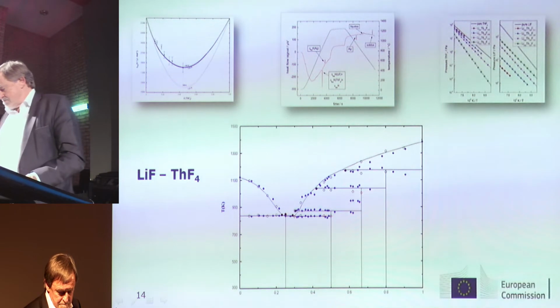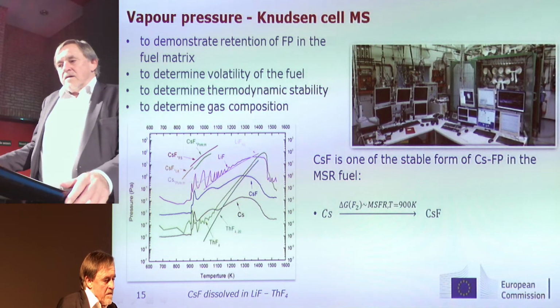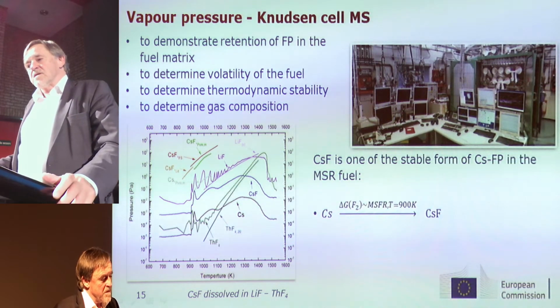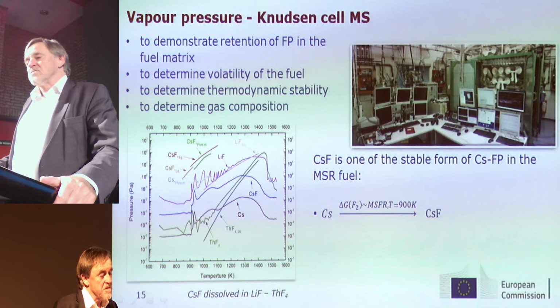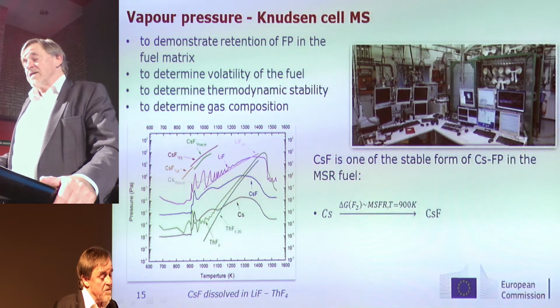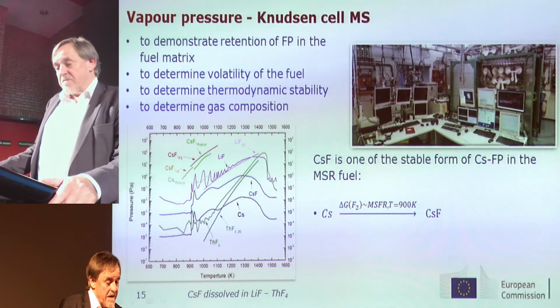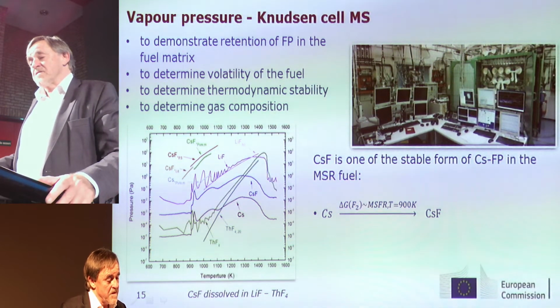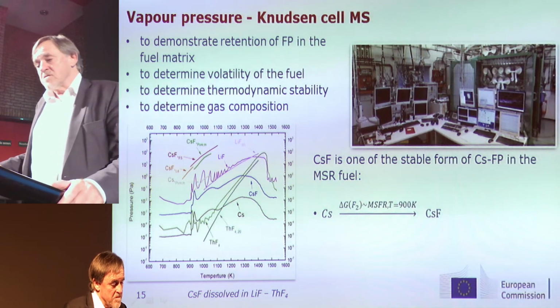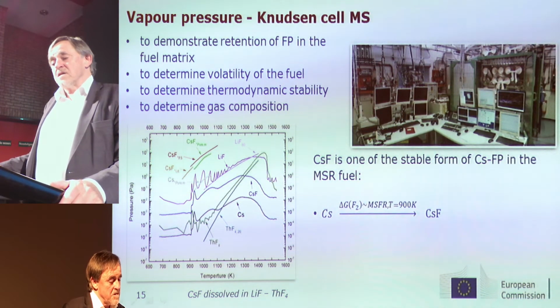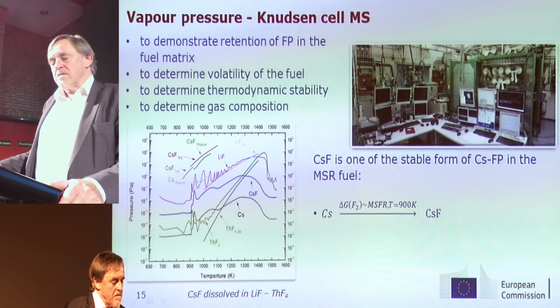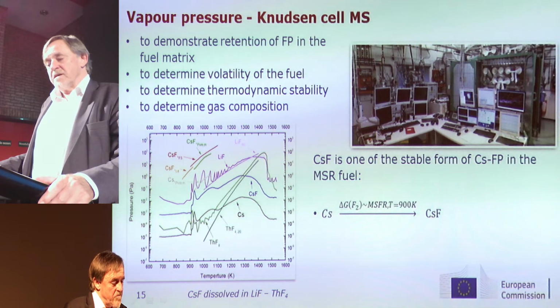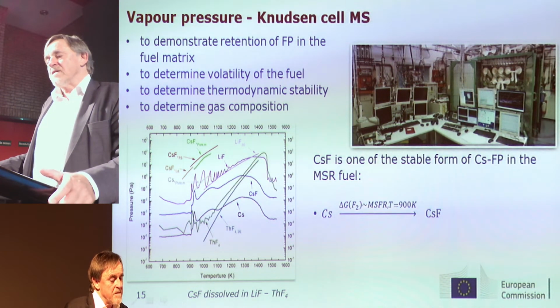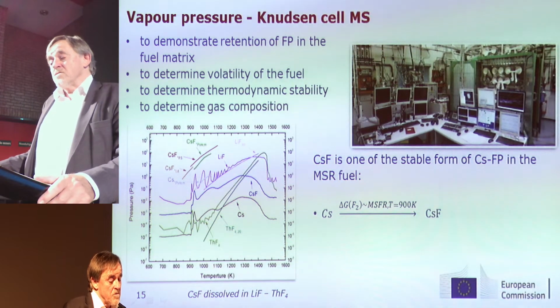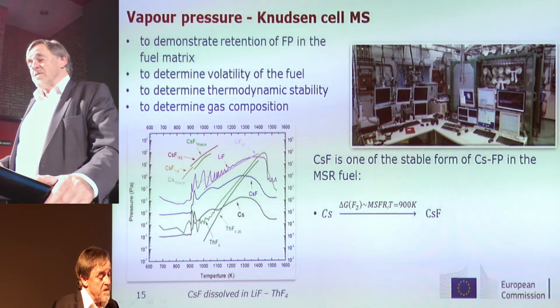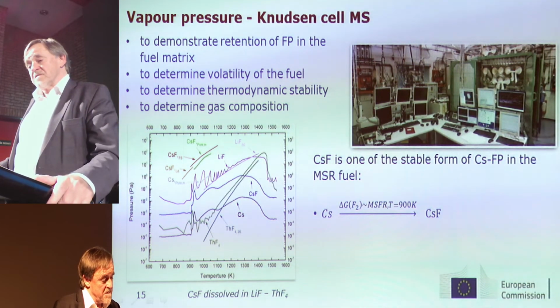For the vapor pressure, we have in our institute a system which is called Knudsen cell mass spectrometry, which can deliver very good data. And we use this mainly for solid fuel material, but in this case we have tried to adapt this method also for the molten salt. Especially interesting is, of course, the discussion about the cesium fluoride, because the claim that cesium fluoride is completely retained in the fuel needs to be proven, and we think that this technique can contribute to provide reliable data for this formation of a stable cesium fluoride and also the completeness of this reaction.